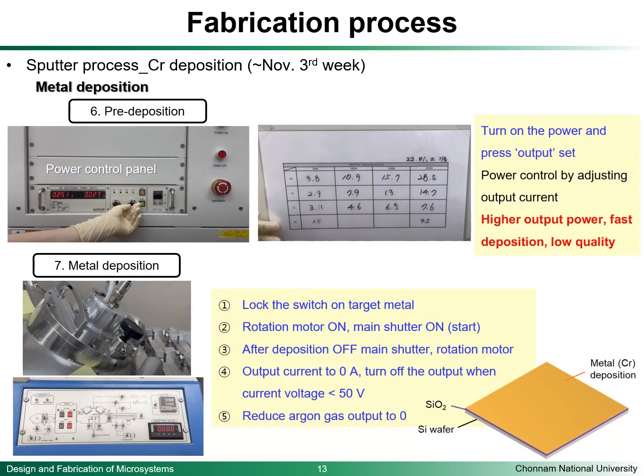The last step of sputtering is control of output power. The output power is directly related to the quality and rate of metal deposition. The higher output power induces a fast deposition process with low quality. So we need to carefully control the output power, and we decided to use the lowest output power of 50 watts for high quality deposition. After the power setting, we can start the sputter process and finish the metal deposition after enough deposition time.